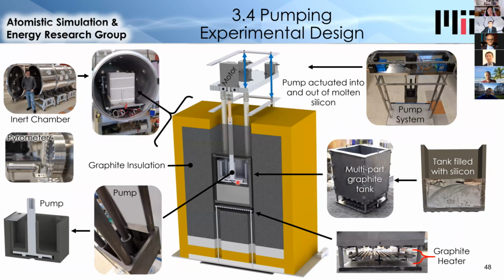So putting it all together, we have the pump in the very center of this figure, which is above the tank, which has silicon in it. Once the silicon is melted, the pump is lowered in by some linear actuators and then turned on. This whole system is operated inside an inert environment of argon or helium inside the chamber shown here, and the temperature is measured with a pyrometer shown on the left. The heater is shown on the bottom right.